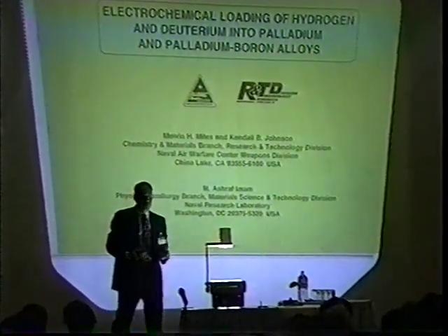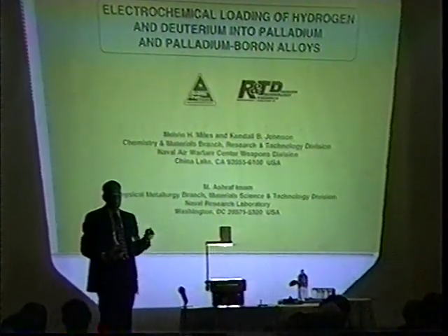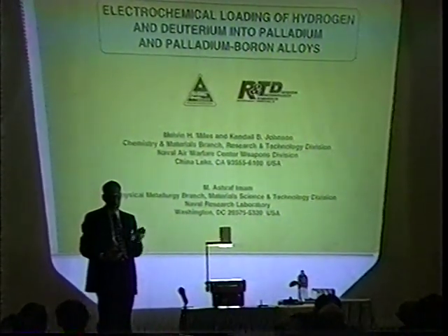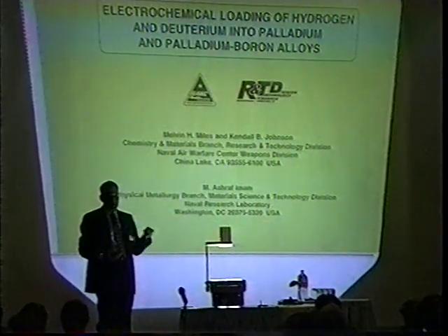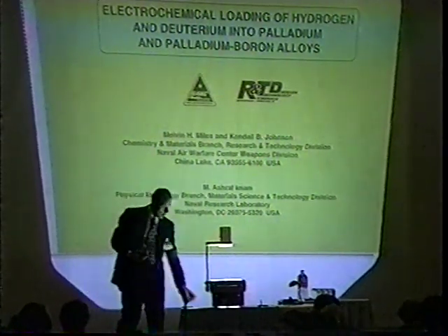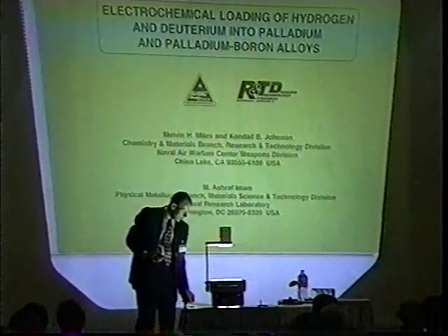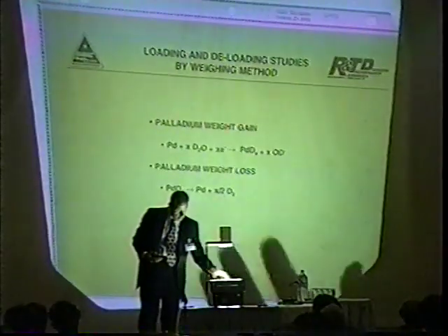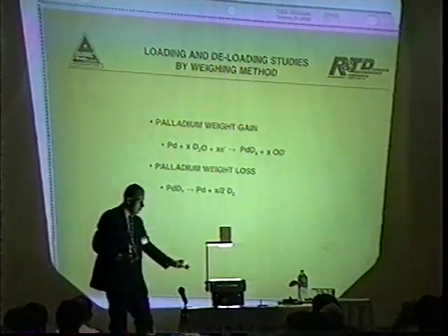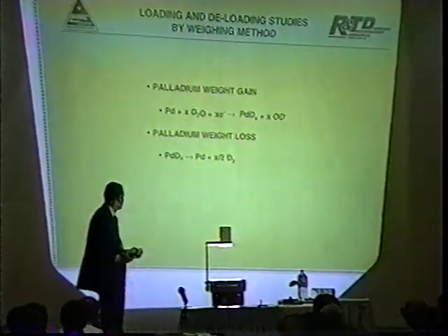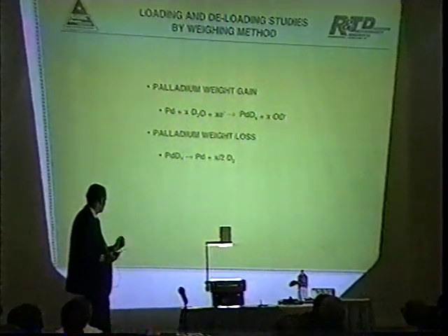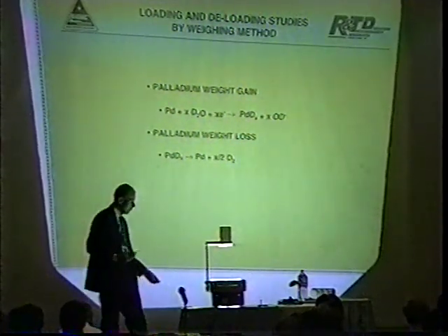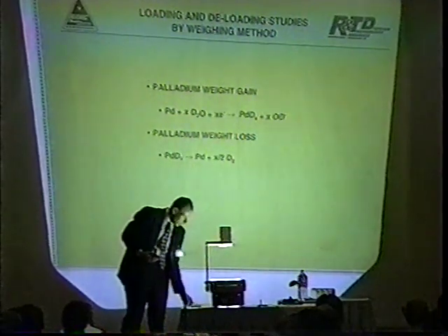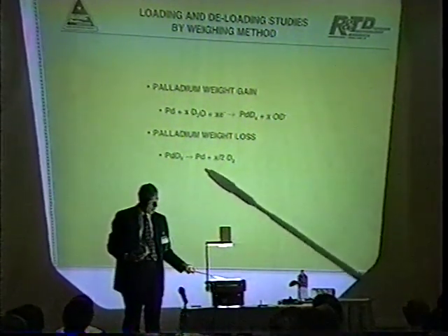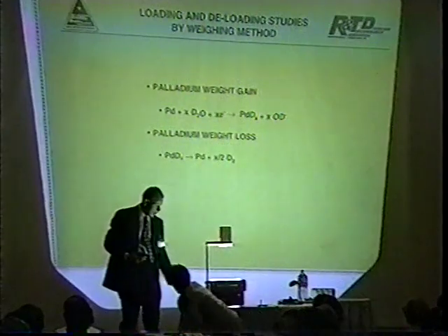Actually, you would do measurements, take the liquid out of the solution, dry it, and then you'd weigh it every minute for 10 minutes. Then you extrapolate back to zero time and get the initial loading at the time you could get out of solution. These are the reactions, of course, as it loads. You get gain weight as deuterium goes into the palladium, and then as it deloads, you have the deuterium coming back out.